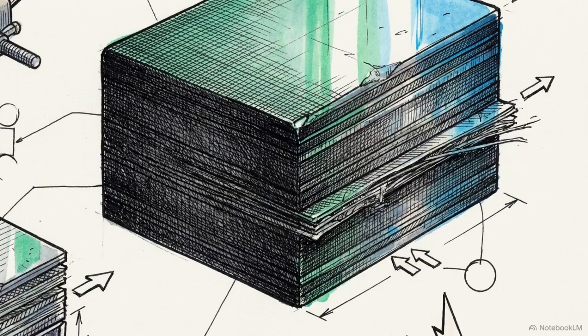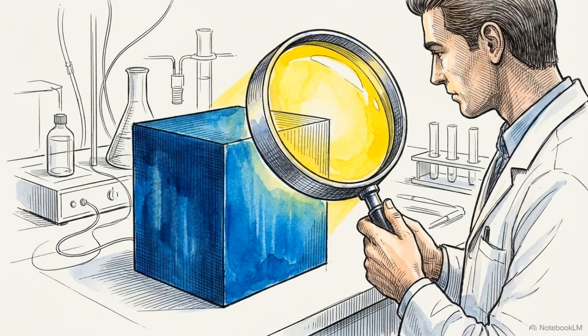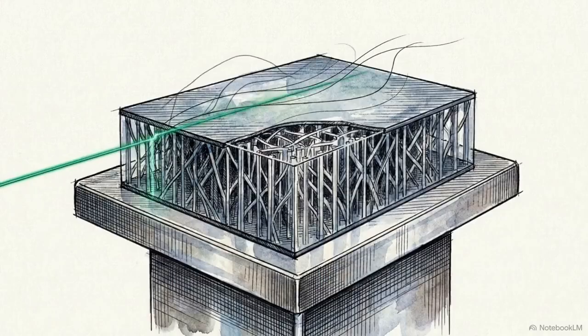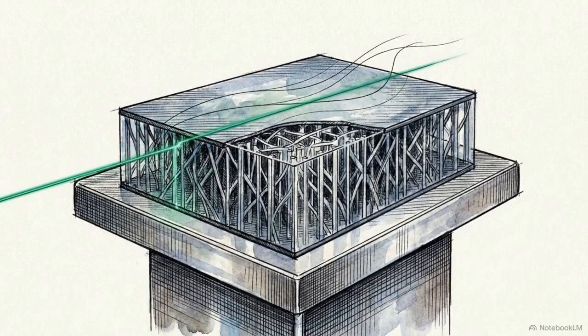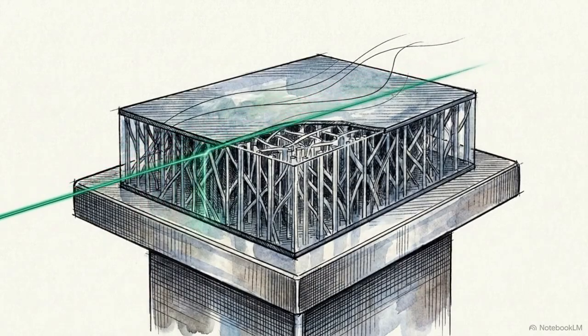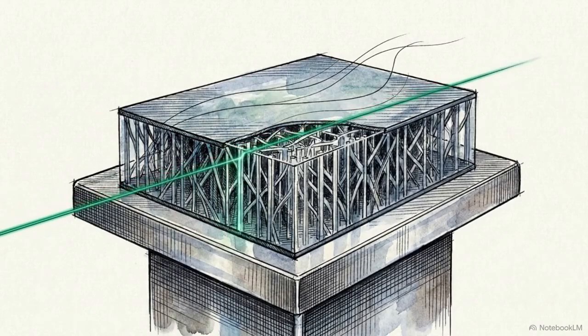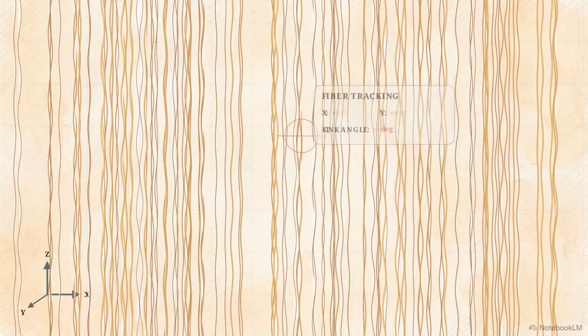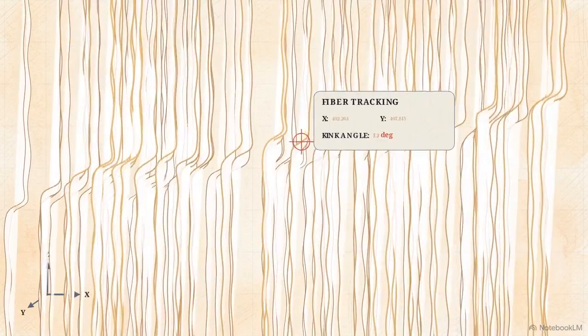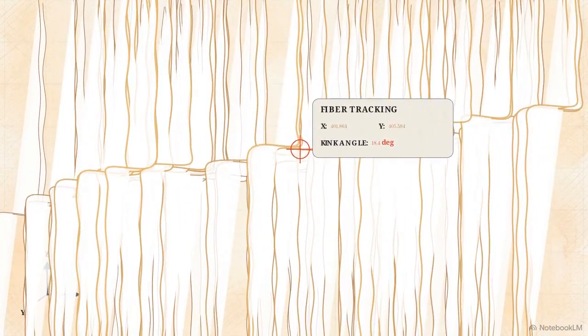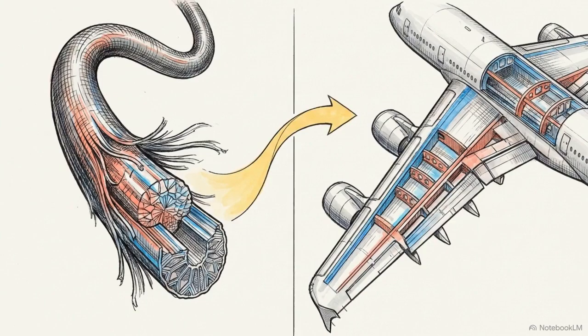Because this transition is nearly instantaneous and happens deep within the material, researchers have historically struggled to observe the exact sequence of the collapse. To bypass this, researchers are using in-situ X-ray computed tomography. By scanning the composite while it is under a compressive load, they can track the 3D movement of individual fibers as they approach the point of failure. Increasing the reliability of composite structures depends on understanding why this microscopic failure occurs and how it propagates through the